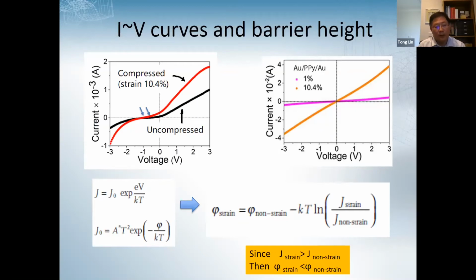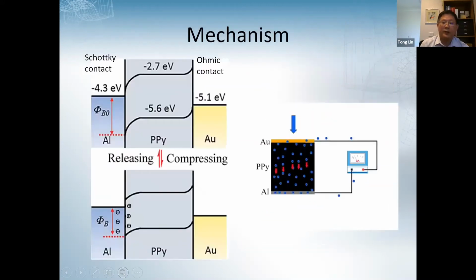So based on the classical equation, we can calculate the barrier height of the Schottky junction. So these are the calculation equations, and we found that on compression, the barrier height is reduced for our device. So based on the experimental result, we propose an energy conversion mechanism here.